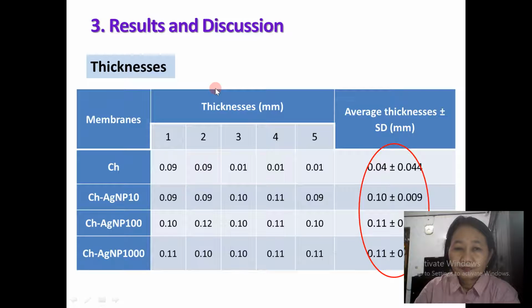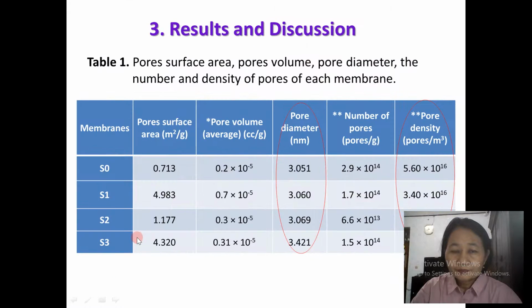Result and discussion. For the thickness of the membranes, we found that the thickness is increased as the amount of silver nanoparticle added increases. For the pore diameter, the pore diameter of the membrane is increased as the amount of silver nanoparticle added increases. Also the pore density of the membranes is decreased as the amount of silver nanoparticle added increases, except for the S2 membrane. The pore density is increased.